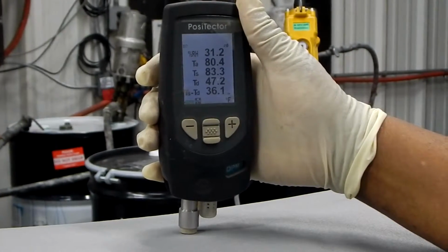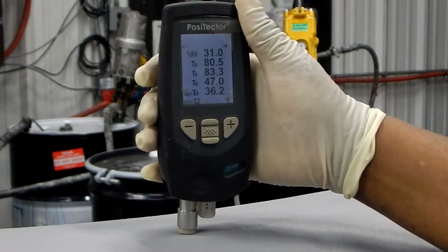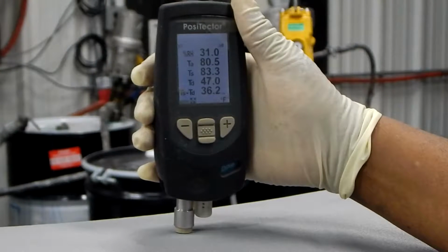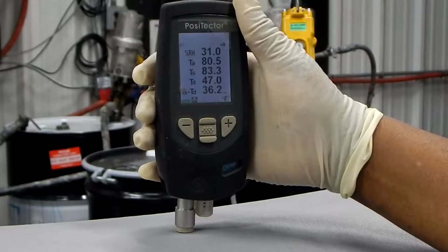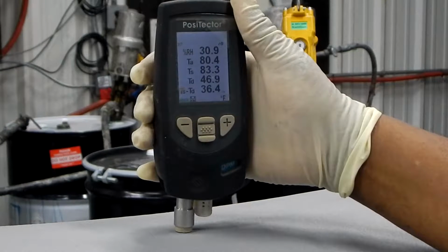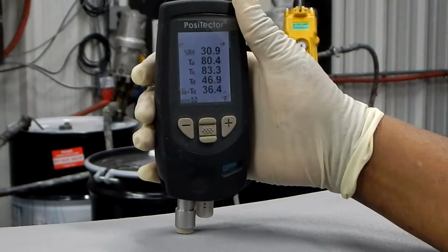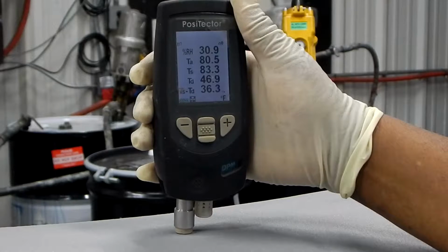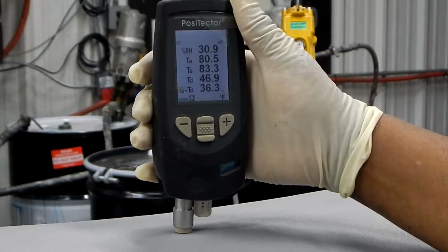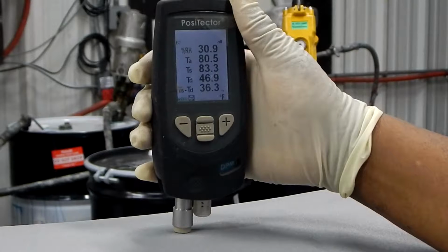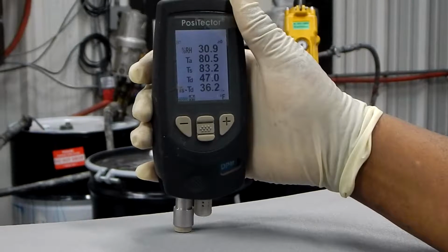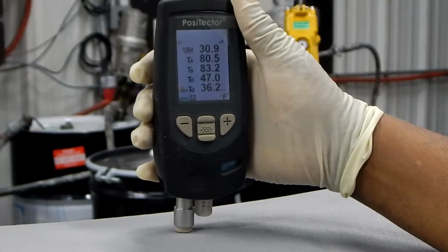Step 9. Verify coating storage conditions. Coating storage conditions are the conditions in which the coating materials and pieces are being held. This step is to measure the air temperature and make sure that it is within the acceptable boundaries to get a quality final product. Use the hygrometer and view the TA reading. Verify that the TA is between 40 and 104 degrees Fahrenheit.